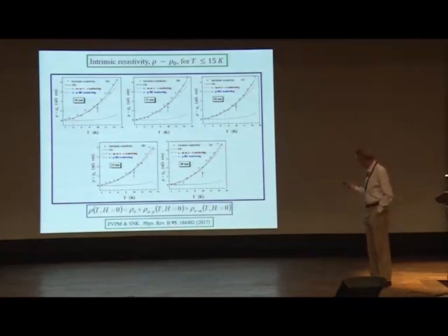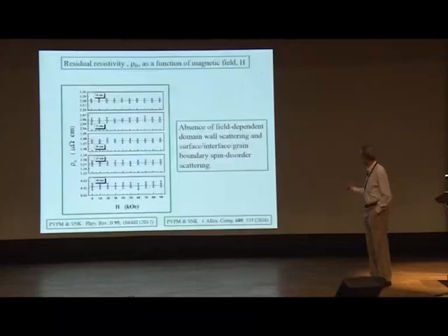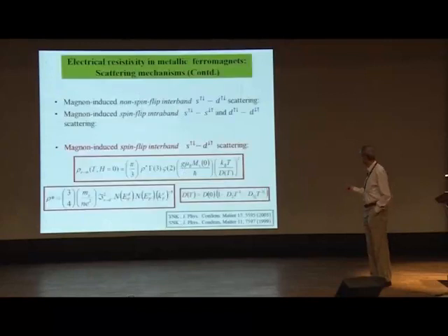If you recall, just go a few slides back. The electron-magnon contribution can also go as T square, provided there is no thermal renormalization of the spin wave stiffness. That means the spin wave stiffness is constant and doesn't depend on temperature.